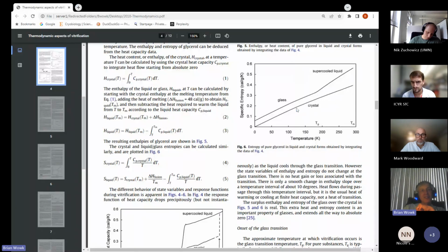And the Kauzmann paradox is that if you waited longer, then naively, the entropy could even become less than the crystal, which is physically impossible. People have come up with different theories for what avoids the Kauzmann paradox or the Kauzmann catastrophe, but it's not of much practical relevance, because the amount of time you need to wait for the glass to relax enough to get close to the Kauzmann entropy is probably longer than the lifetime of the universe.